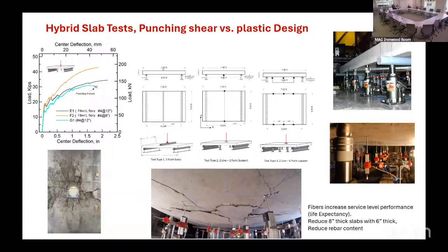And we have done these projects for SRP. You can see on the bottom, many times structural engineers are worried. So what you see, the hole, it's called a punching shear behavior. The slab is so thin that, like a stapler, it punches out. But if you have fibers, you completely get away from that shear failure, and now you have a distributed crack system that the system doesn't give up. And these are the type of experiments that we've done for plastic design, making and testing these panels.